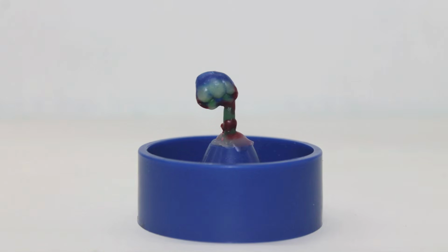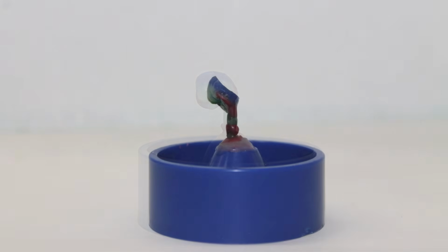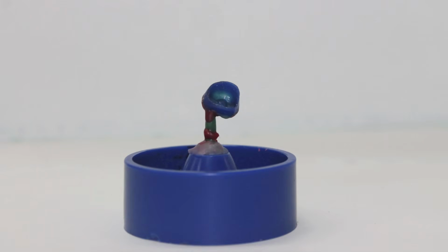The sprue former should be just long enough so that the highest point on the wax pattern will be 6 mm from the end of the ring. If the pattern is too close to the end of the ring, the molten alloy may blast through the investment during casting. If it's too far, gases may not escape rapidly enough to permit complete filling of the mold with alloy. To provide adequate bulk of alloy during solidification, the sprue itself should be no longer than 6 mm.